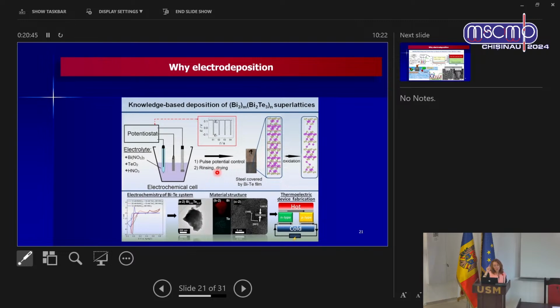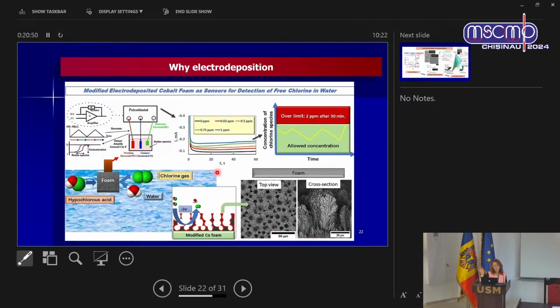And also mentioned by Henrikas a little bit in his plenary talk, we also developed during these years a very nice sensor of cobalt foam, electrodeposited cobalt foam. You see a very developed structure which allows increasing the signal of free chlorine detection in water. And like this we can control the chlorine in the water.